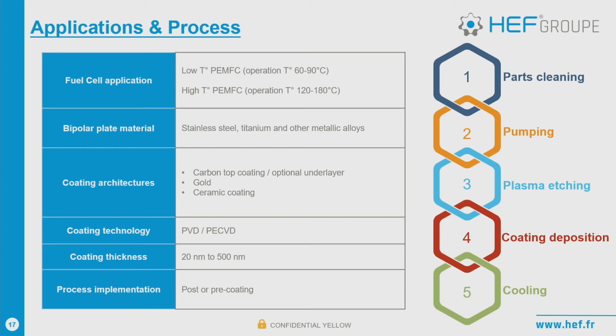So we are working for low temperature fuel cell and also high temperature fuel cell, which are used in aviation and where the weight is a real problem. We are coating several materials. The main ones are titanium and stainless steel, and we can do several coatings. The most efficient one is gold. Gold is too expensive, so we have developed a carbon coating, which is really, really suitable for this application.